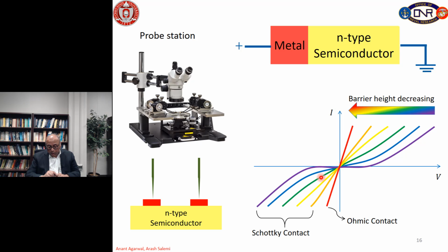Now, it also depends on what temperature we have deposited the metal. So, this is the case of nickel on top of silicon carbide N+, and you can see if we do not anneal the nickel at high temperature, then we will not form the nickel silicide, and we will have rectifying characteristics between these two contacts.